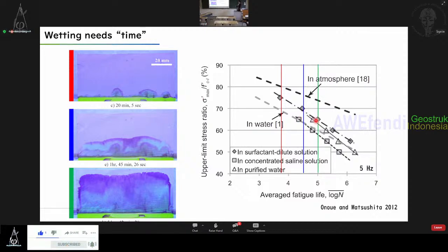And how does water penetrate in such a short period? Probably it depends on the microstructure or cementitious composition. But for example, Professor Wong's research shows how water penetrated in a short period. At 20 minutes, you can see a very small amount of water penetration. Afterwards, water slowly penetrates, and at 3 or 4 hours, it is close to fully saturated. So what these comparisons show is that here there is not so much water, but here water penetrated.